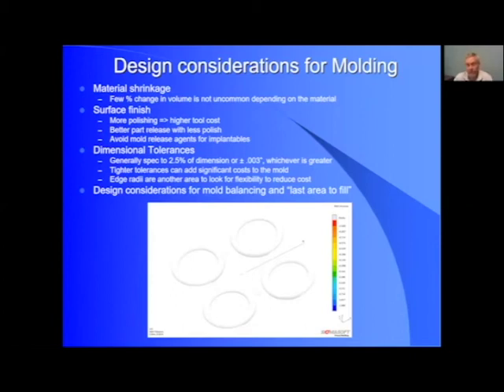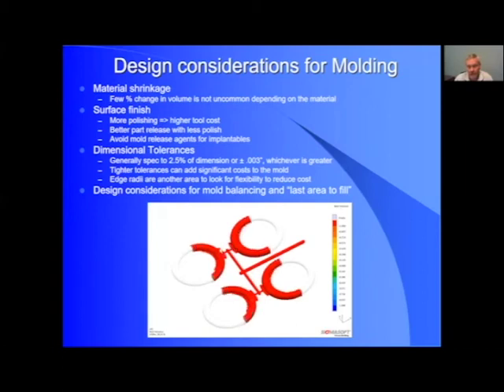So again, in relation to the previous slide that talked about tear flash and minimizing flash, you definitely want to consider the pressure balancing, the flow balancing of the mold in the last areas to fill. So I thought I'd share with you a simulation that we did recently on kind of a model vaginal ring. And you can see here as I start the simulation that the material coming in from this side and filling a four cavity ring mold. So you see, this is what they call the runner. These are the gating where you have a tab gate so you get more uniform filling.